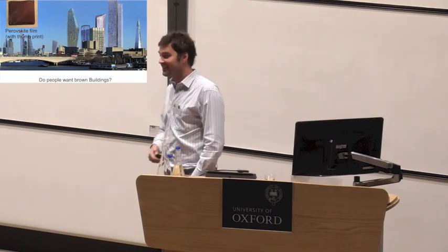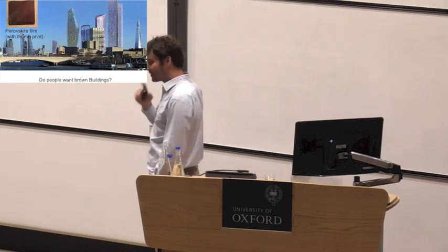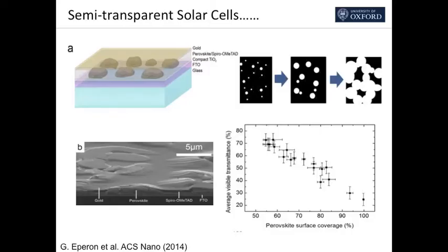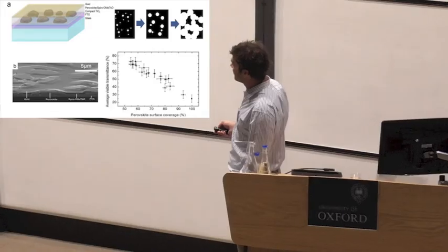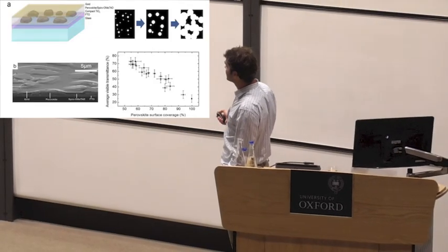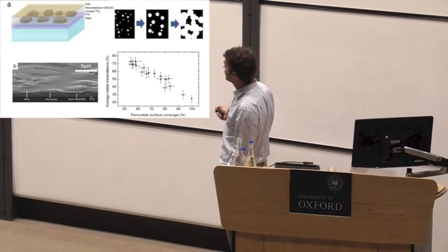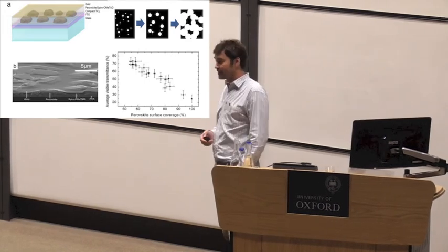So what can we do? What we discovered was we can actually make these films with the semiconductor form little islands, and then they're semi-transparent. The light passes through the gaps between the islands, and the little islands act as little solar cells. And we control the transparency from 80% down to practically zero, and the solar cells actually work. So what we get is a semi-transparent, neutral-coloured photovoltaic device.